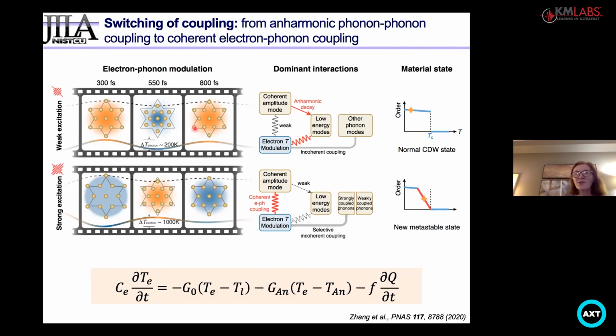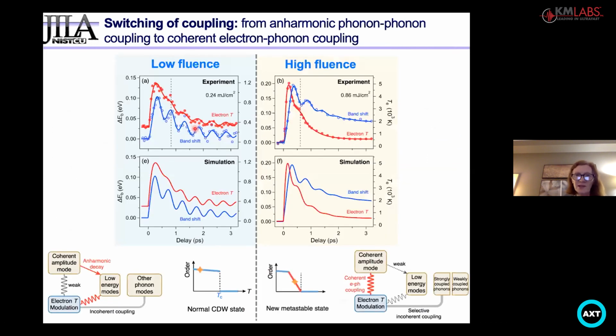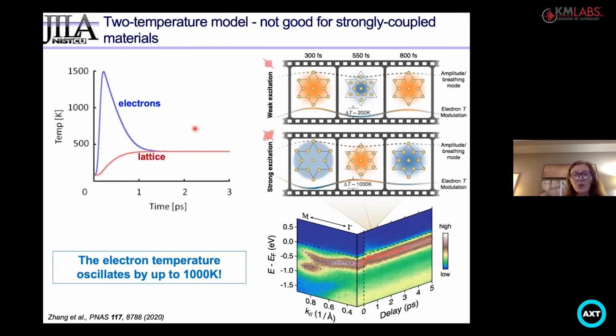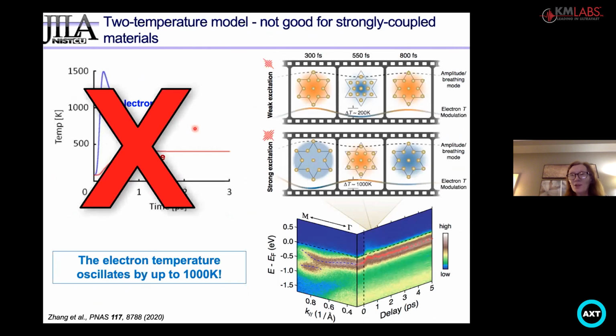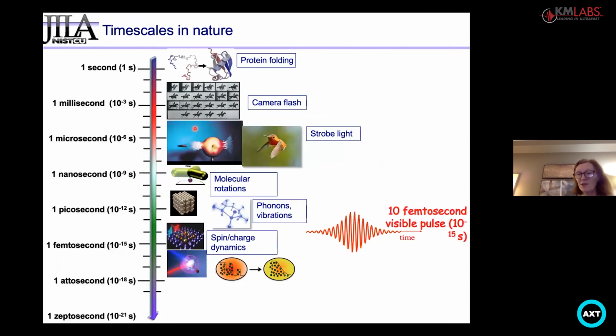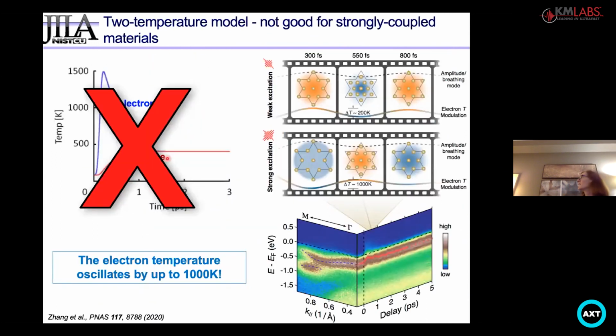In some cases, interacting coherently, in others, incoherently, in other cases, inducing anharmonic decays. So what we learned is the two temperature model does not work for strongly coupled materials, and there's some beautiful ways one can manipulate these materials with light. And I think at this we go to 5 minutes.